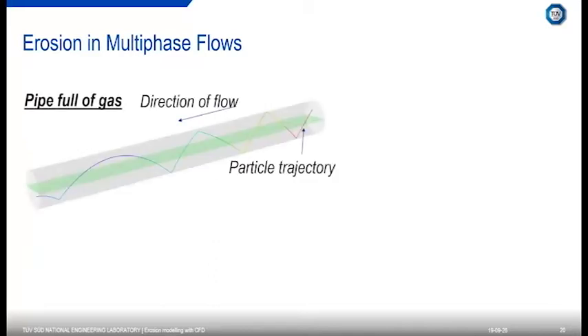Let's complicate things even more, why not? Let's consider erosion in multi-phase flows. So if we have this theoretical example where we have a pipe full of gas, and let's say it is moving at 1 meter a second from right to left, and we put in a particle, and this particle has a velocity of 2 meters a second, but it's coming in at a 45 degree angle towards the bottom of the wall. The green line in this just represents half of the pipe. So the particle will come in, it'll bounce, it'll gradually lose momentum, and eventually it exits the geometry.